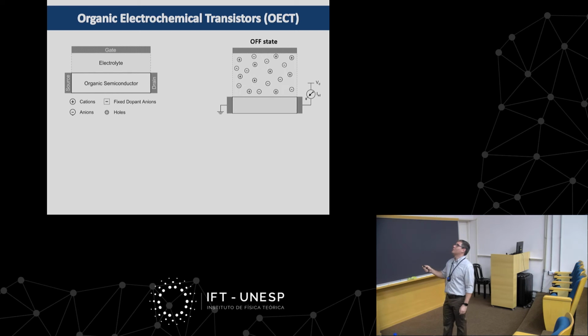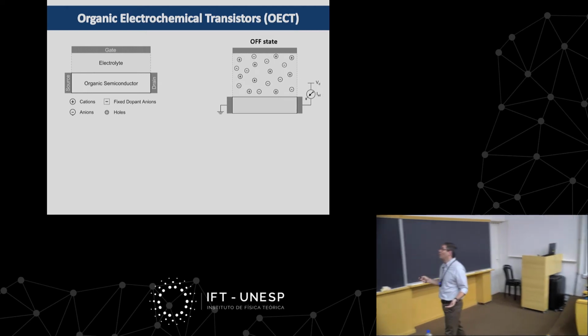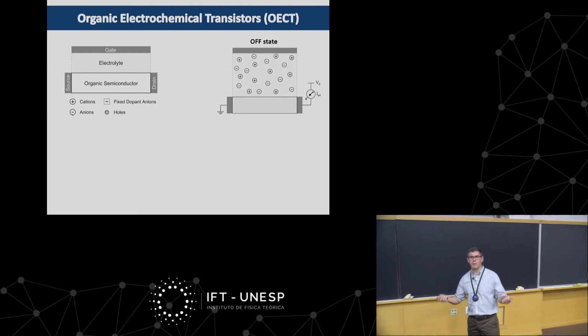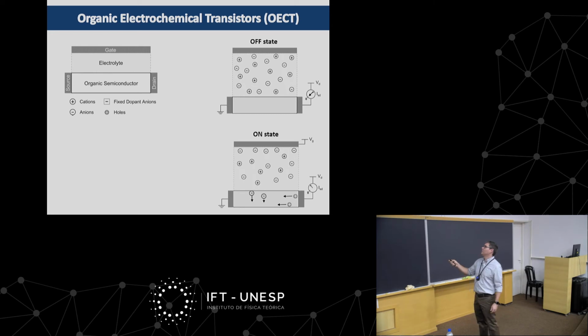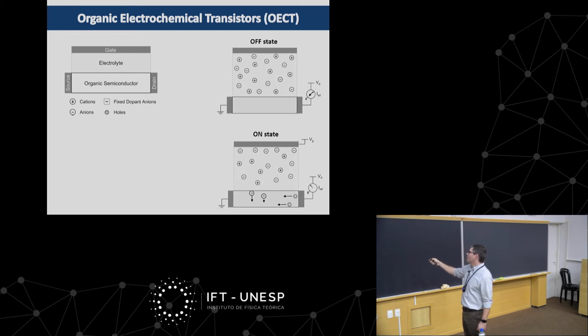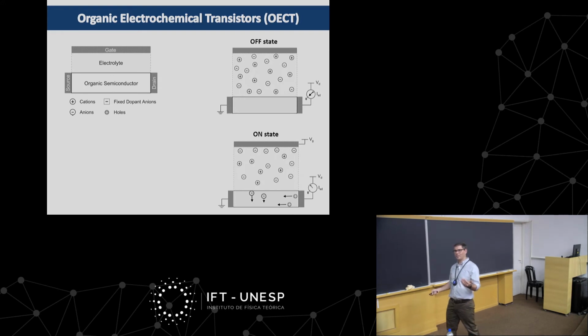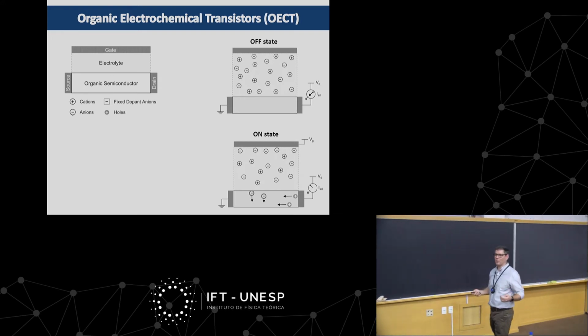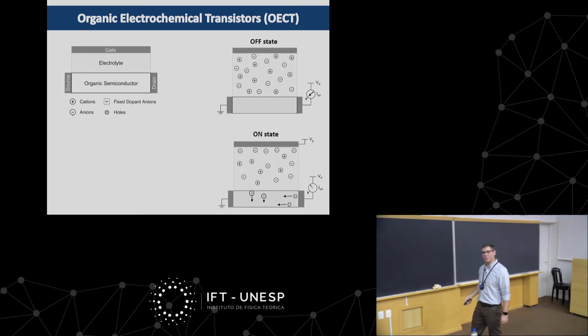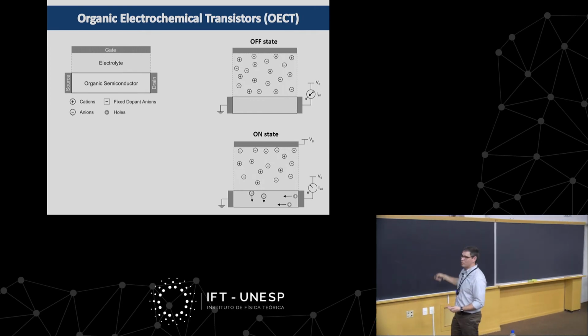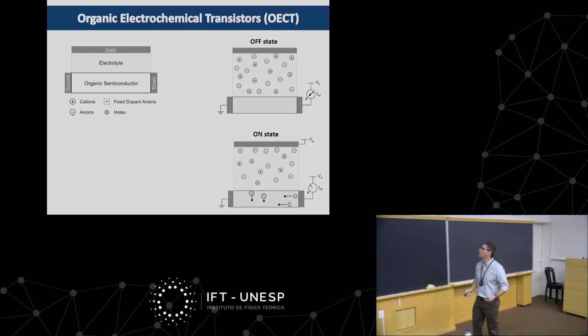So if I don't apply any potential to the gate, I can apply a potential between my drain and source, but no charge is coming into the polymer, and therefore my current between the drain and source is basically zero. But when I apply a voltage to my gate, here I'm applying positive, so I'm pushing negative ions into the polymer. And for the same reason, the thermodynamic equilibrium that I mentioned before, if one negative ion goes into the polymer, it is required to maintain bulk neutrality that my drain or my source inject into the polymer a positive hole, or remove an electron, if you want to think about it. It's the same thing. So two ions here, two charges here. You see you have a translation between one ion going in and one charge coming in. And therefore you have a one-to-one translator between one and the other.